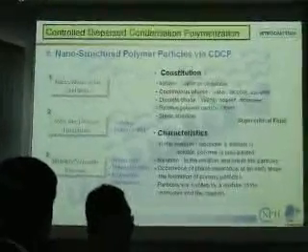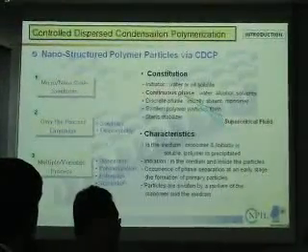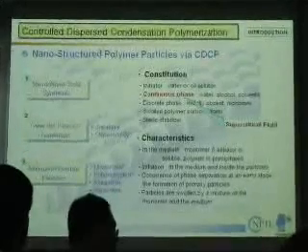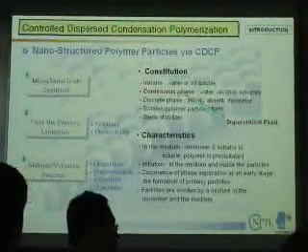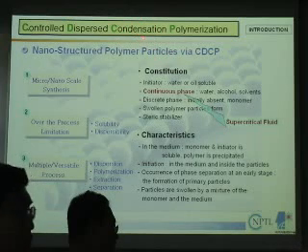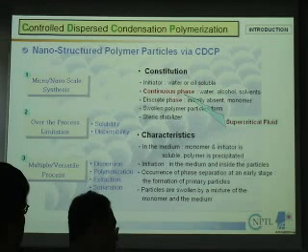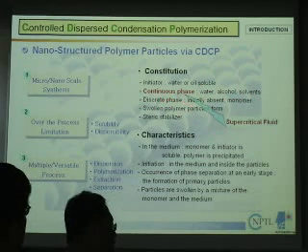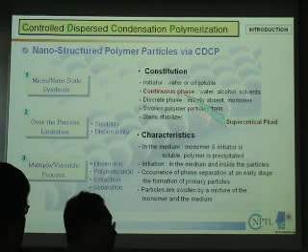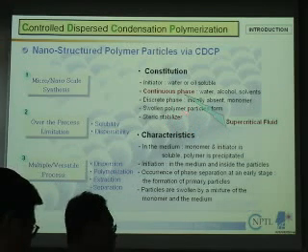You already know about the dispersed polymerization, so I'm not going to go in detail about that, but for that I add this condensation process into this dispersion polymerization. That means you have initiator in water or oil soluble system, and continuous phase you have a water, alcohol, solvent. And discrete phase initially it is monomers, now it turns into the polymers. And swollen particle forms, and you need to have some kind of stabilizers to make the droplet or final particles.